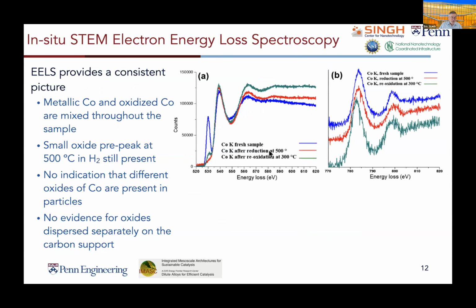Similarly, we can complement that with electron energy loss spectroscopy. It's a consistent picture. We see that we have both metallic cobalt and oxidized cobalt oxide samples throughout. Depending upon which particles we look at, we will see either purely metallic or some oxidized sample. We often see a pre-peak that's present even after 500 degrees in the reductive environments. That's this little bit of red here before the edge, which indicates that there's still a small amount of oxygen present. Overall, we can use electron energy loss spectroscopy to discriminate between individual particles and show how they make up the overall average that's observed by the X-ray absorption.